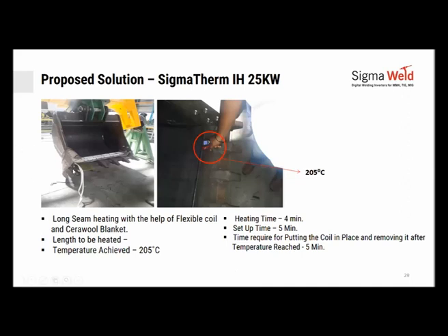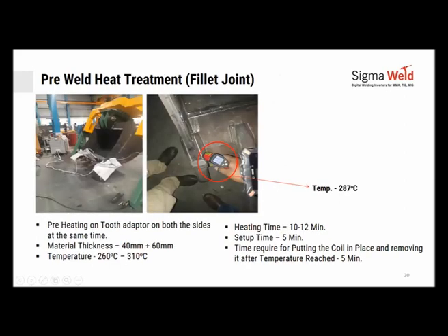The way to do it with induction, we place the coil here, a simple blanket, several blankets below it, and you could achieve 205 degrees in under 5 minutes. Again, the operator could simply pick the coil, put it on the side, and start welding. If you had to do this with the help of a gas-based furnace, you can imagine this would take at least 20 to 25 minutes to preheat. To remove the gas burner from there and get the welder to start welding would be another challenge.